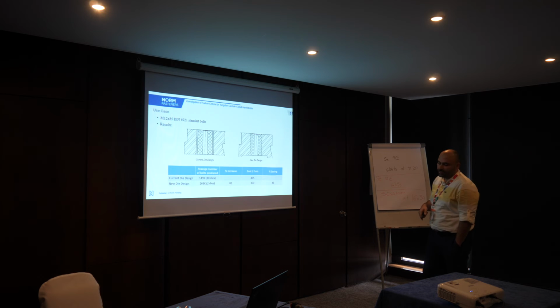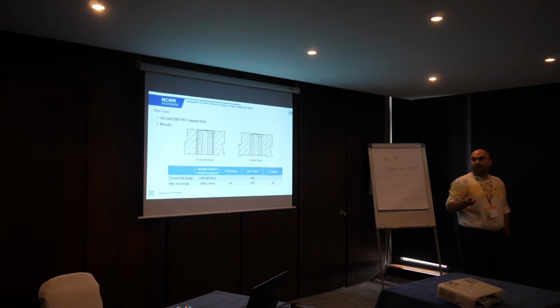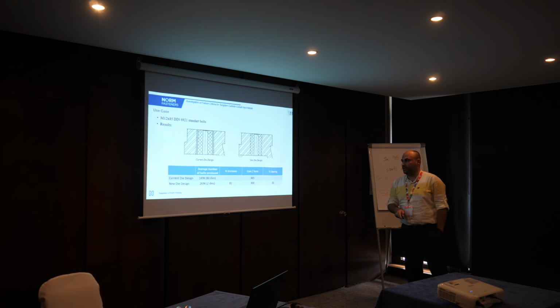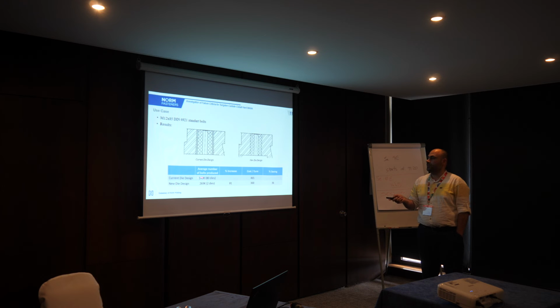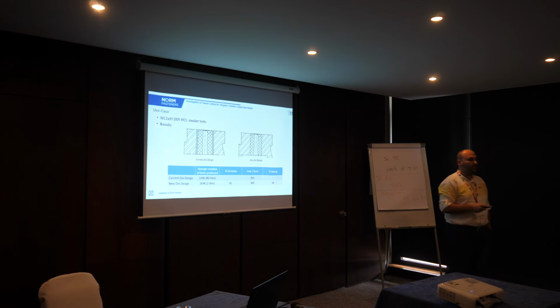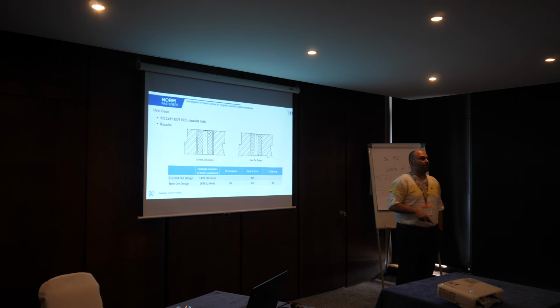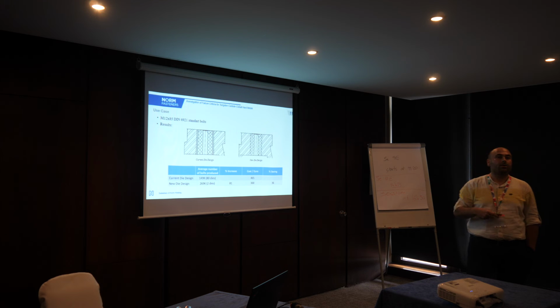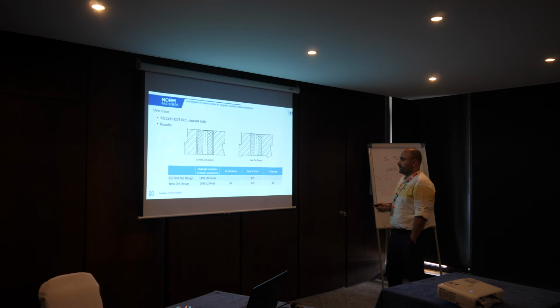So this is the current design we are already using, and with this new failure criteria and the pre-stressing ratio, we were able to simplify the design. And when we compare the performance of these two, the average number of bolts produced per die is 149 for the current design, and 269 for the new design that we came up with, applying the Mohr-Coulomb failure criteria, and with the optimization for the pre-stressing. So it's a significant increase of 81%.